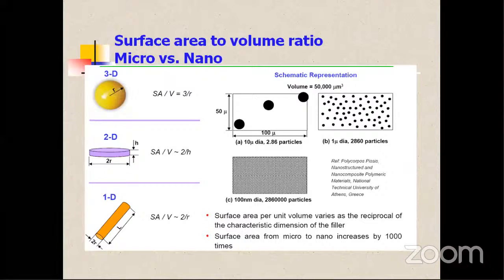And from these three rectangles, figures A, B, C, if you refer to them, I have selected three particles of weight equal to W, where each diameter is 10 microns. And this is the area, 50 micron by 100 micron. If I want to disperse those particles, one scheme, what I have shown here, looks like this, almost 2.5 particles are within that surface. So this is not a good dispersion and will not give good properties, even though it is a micro composite. But look at this second one. I have taken that same weight, three particles only, and crushed them further by ball milling so that you have more number of particles and the particle size gets reduced.